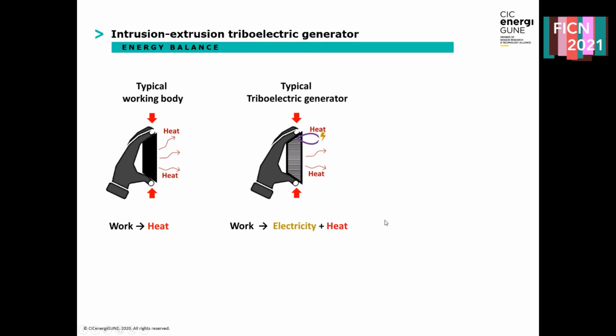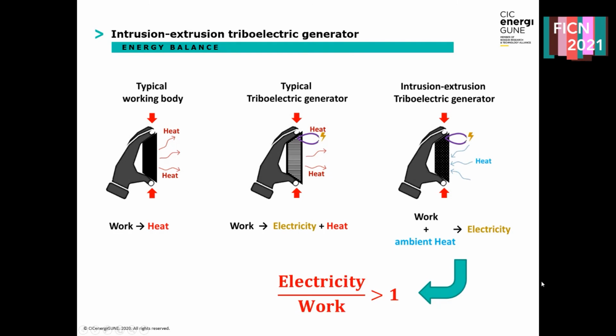Now, for triboelectric generators, typically the energy balance looks something like this. The work supplied to the system is transformed into electricity with some heat losses during the process. And what is fascinating about this intrusion-extrusion concept is that during the compression, the system absorbs environmental heat, and via triboelectrification can convert this work and heat into electricity. With this regard, the coefficient of performance, which for applications is typically measured as the ratio between electrical output and work input, can actually be greater than 1. Something which is quite fascinating to explore.